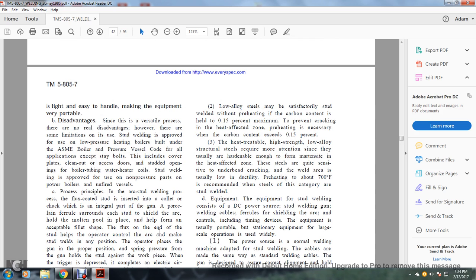Low alloy steels may be satisfactorily stud welded without preheating if the carbon is held to 0.15 percent, to prevent cracking of the heat affected zone. Preheating is necessary above that carbon content. The heat treatable and high strength low alloy structural steels require more attention, since they usually harden enough to form martensite in the heat affected zone. These steels are quite sensitive to underbead cracking, and the weld area is usually low in ductility. Preheating to about 700 degrees Fahrenheit is recommended when steels in this category are stud welded.